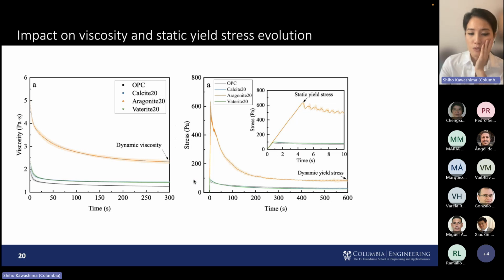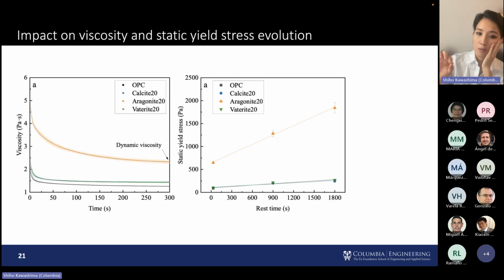And then we imposed the intermediate strain rate at various rest periods, and these are typical responses. Again, the calcite and vaterite seem to have minimal effect on rheology, but with the aragonite, there is a significant increase in this peak, which can be taken as a static yield stress. And so we took that peak and then measured it over time. And these are including error bars. So there's this dramatic difference, right, in the flow response of paste with aragonite addition compared to calcite and vaterite.